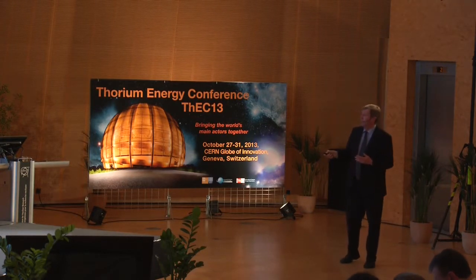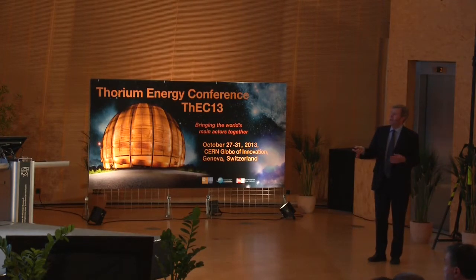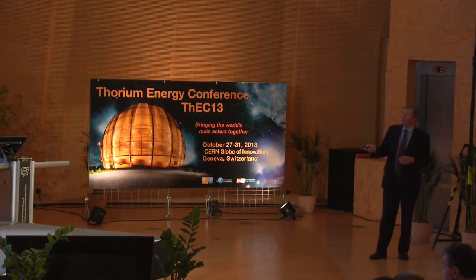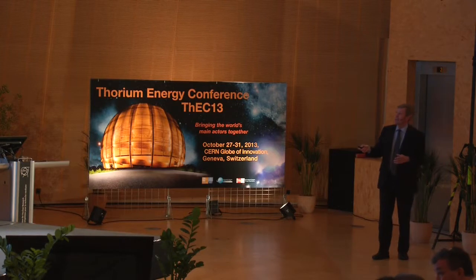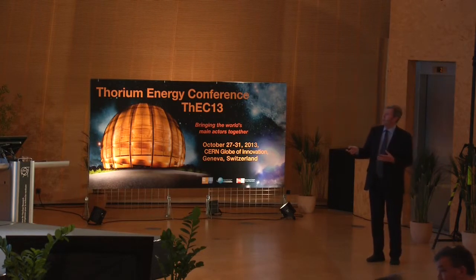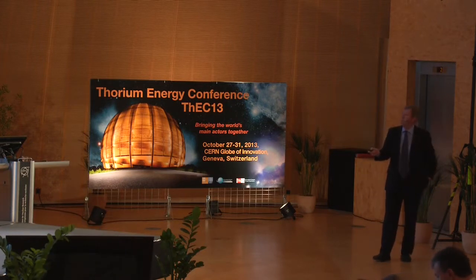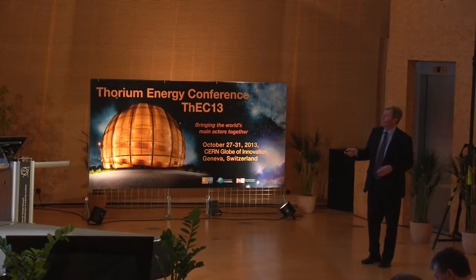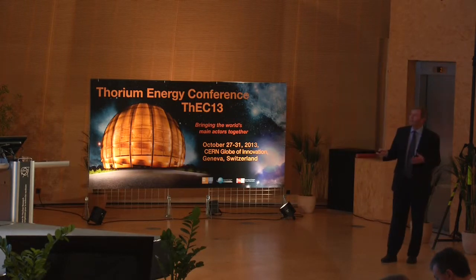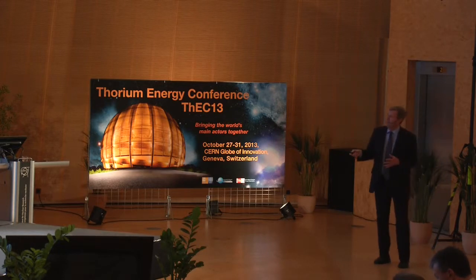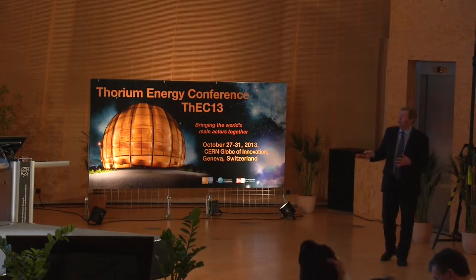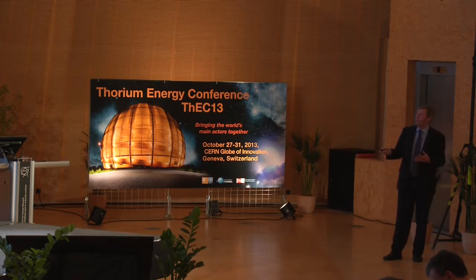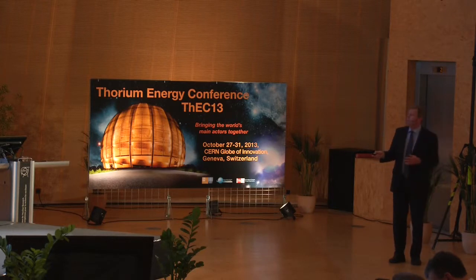So here's the core of the reactor. It's aiming at generating 1.5 gigawatts. It will run with a solvent system, which is a lithium fluoride, thorium fluoride eutectic, and it will run either with uranium-233. The design has been done with uranium-233 at about a 3 or 4% level in the salt, or alternatively a startup composition made of plutonium and minor actinides. There'll be a fertile blanket which surrounds the reactor vessel, and the kind of physical properties that we'll be dealing with here in this system is its operating temperature should be in this regime. As we'll see, the lower bound here is really set by the freezing point of this mixture, albeit a eutectic, and the upper limit is really to control the corrosion in the solid elements.